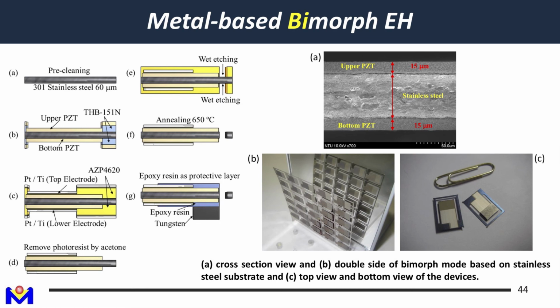The other advantage of stainless steel is that it is itself a metal, so it can be used as a ground connection point. Then we remove all the photoresist, cover it with another photoresist, and do wet etching to release the beam shape. Then we anneal at around 650 degrees C, and in the final step, we glue a proof mass on the tip to lower the resonant frequency. So this is the final device we fabricated. It's about the size of a paper clip, and our substrate is stainless steel. We start from a rectangular substrate, 10 by 10 centimeter, instead of a typical circular silicon wafer.